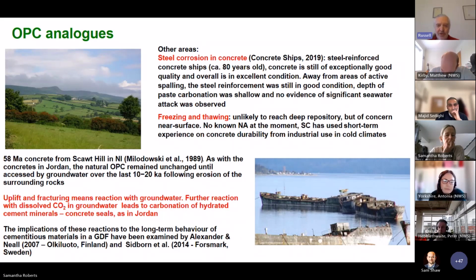And for other areas, steel corrosion in concrete, for example, natural examples we haven't found yet, but there is information from some concrete ships. It's generally rather qualitative because the work wasn't safety case focused, but it's interesting. It shows that there's very little degradation, amazingly. Another FEP associated area is freezing and thawing. Most organizations think it's unlikely to reach the repository depths, but we can't really address it from analogues. There's none known at the moment. So to date, for organizations such as SKB and Posiva, they've used short-term experience and concrete durability from industrial use, which is completely understandable.